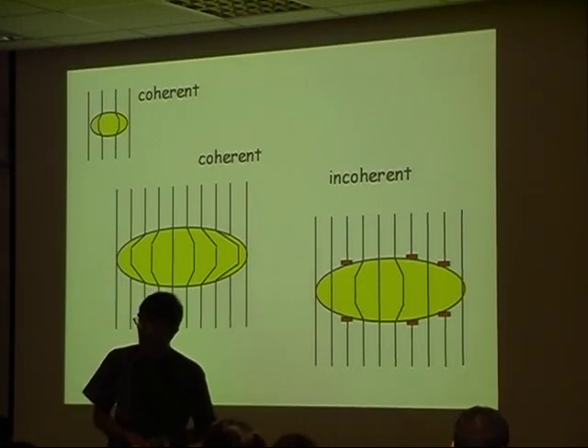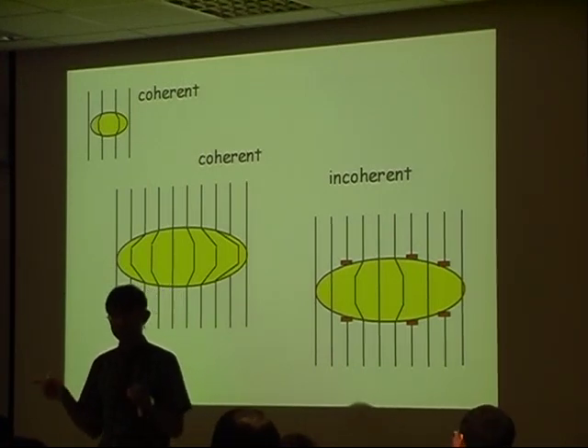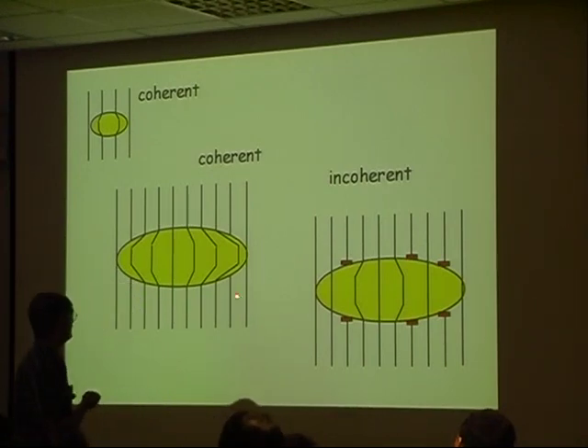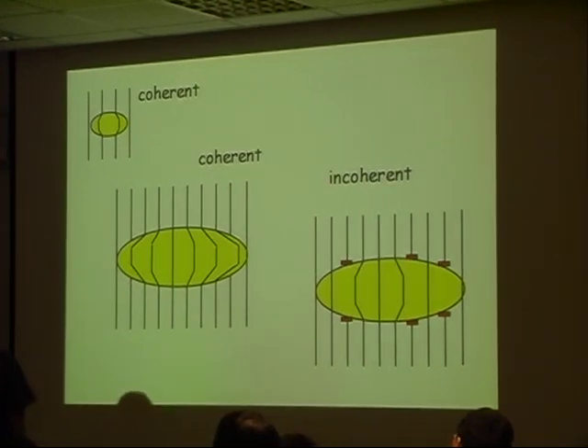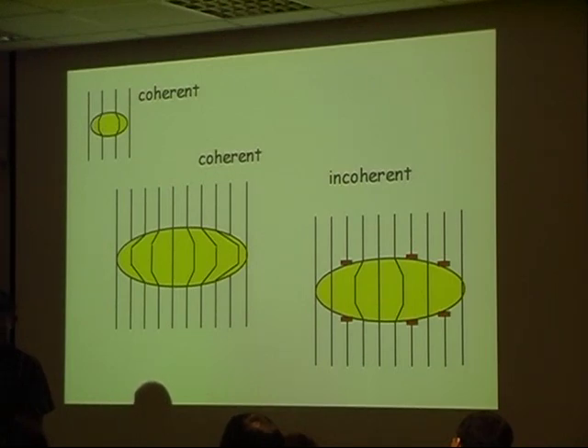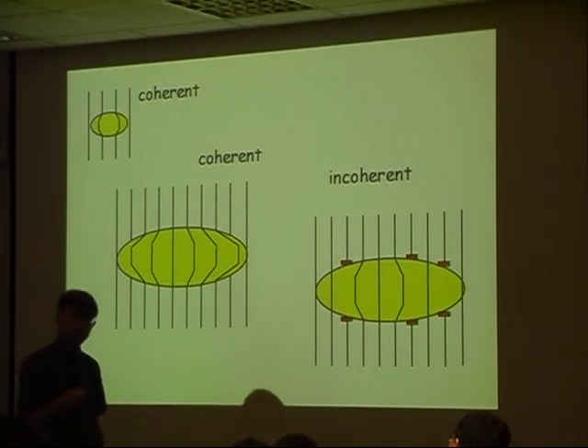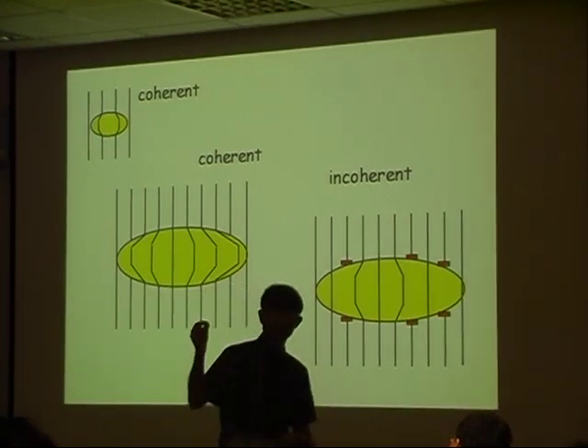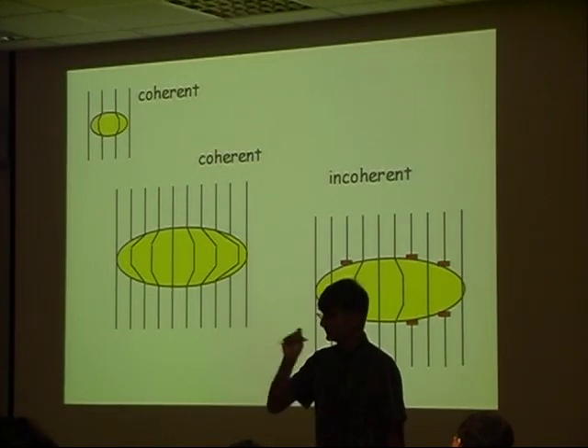Now think about the opposite process, where we are going from a large particle to a small particle. We gain coherency. In the mechanical alloying process, where you create mixtures of very small particles, you start with incoherent interfaces, and then you force them to become coherent. Eventually when this becomes small enough, you completely lose interface energy because it becomes a solution. You don't have an interface around each atom.